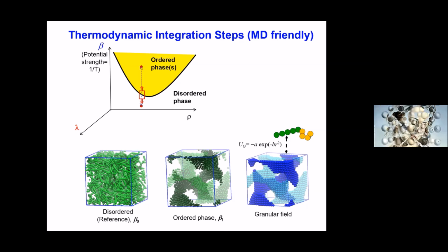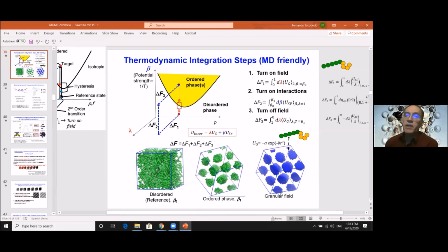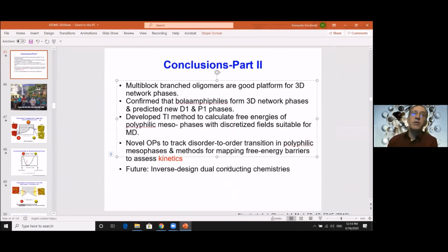But what you are saying, I think we feel it will work fine in the context of coarse-grained systems, where you can do what you are suggesting: I have this phase I want to form, and I can start modifying the force field to match that. The part that we find more challenging is once you go from the coarse-grained description to the atomistic description, because something that is stable in the coarse-grained model may not be stable in the fully atomistic model, and that's where we are still trying to figure out the best way to do that.